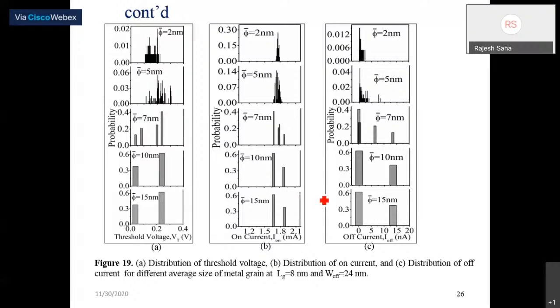For on current also it increases. Similarly, the variation in the off current also increases, and you can see this span. But one thing you observe is that this span is not greater than 0.2. The difference between these two is not greater than 0.2, because the titanium metal gate has a work function difference of 0.2 only.